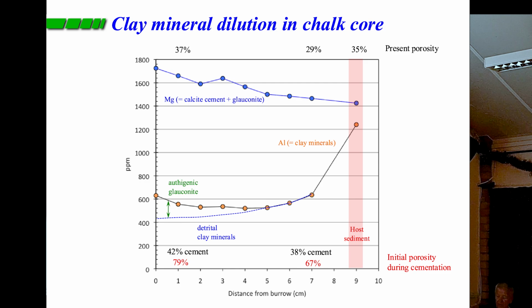With that, you can then translate that into the dilution effect, and that gives you the figures in here. That the initial porosity when it was being cemented, 67% over there, 79% over there. In other words, very, very high porosity chalk. It had only just been deposited. So whatever was happening was happening near surface.